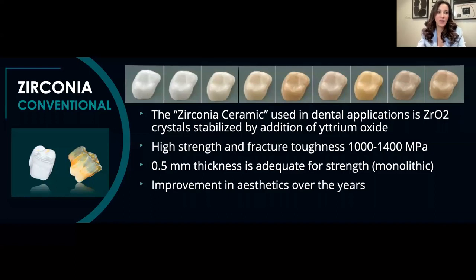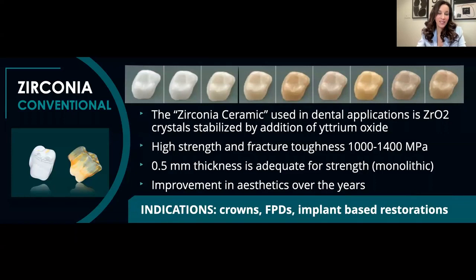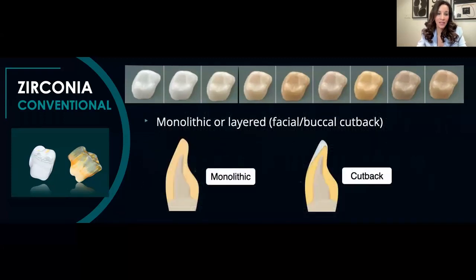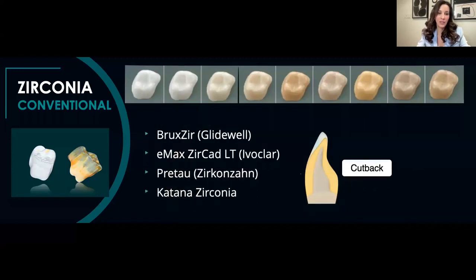So suffice it to say that when we think about conventional zirconia in its monolithic form, its indication could be widespread for crowns, fixed partial dentures, and implant-based restorations. And the preference, the standard, is to have a monolithic material with the ability to cut it back on the non-occluding surfaces. And you can cut back a little bit and layer some porcelain if you wish. Some examples of this material, which you probably see on the screen, are various materials that you use in your day-to-day practice: BruxZir, Emax Zircad, Pretau by Zirkonzahn, or Katana Zirconia. These are all materials that comprise conventional zirconia.